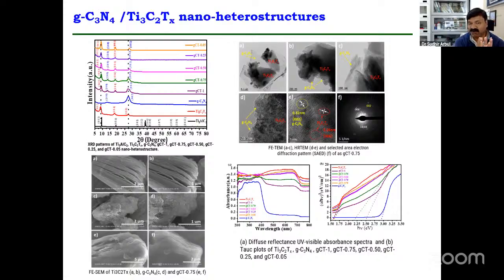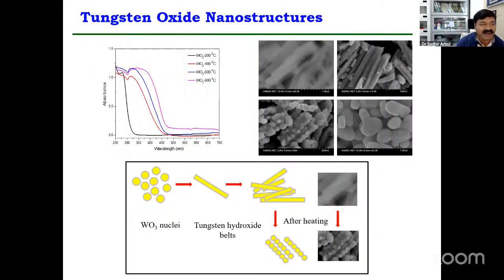See here, for what purpose we are using this technique and what kind of interpretation you are gaining, that is very important. Another case, what we did, we prepared tungsten oxide nanostructures and heated from 200 to 800 degrees centigrade. From XRD, we saw that there is a monoclinic phase, a triclinic phase, and one more phase. But UV-visible spectroscopy also gives you a different absorption profile for the same material with different structure. Okay. See here, at 200, it is hydrated tungsten oxide.